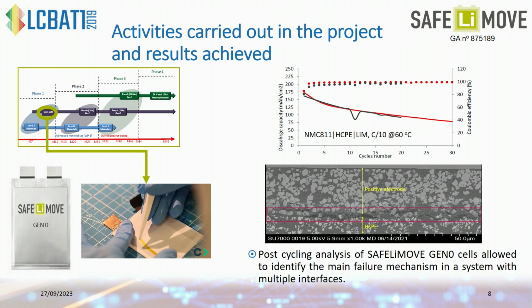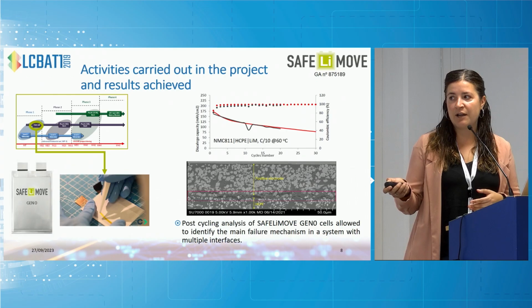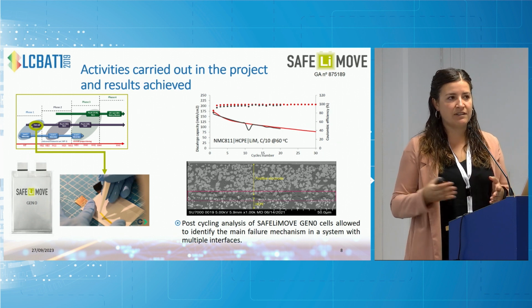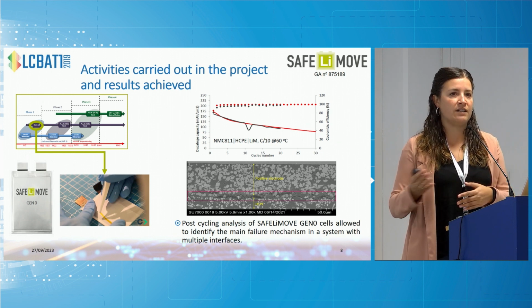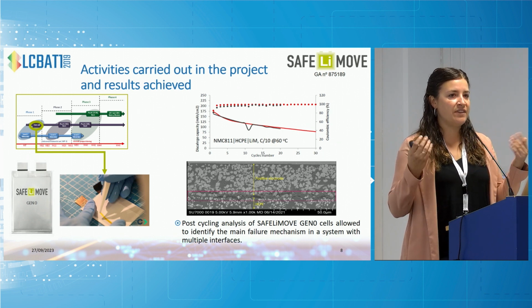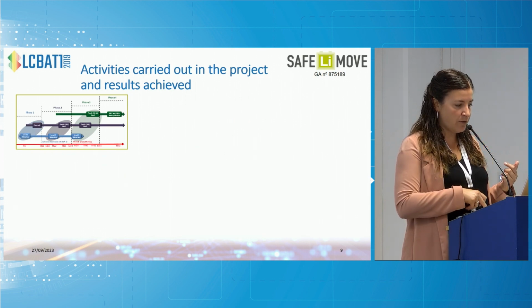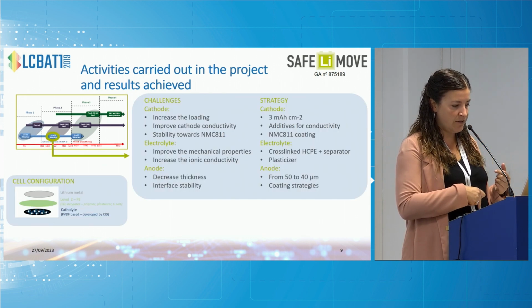And the most important part is that the cycling was used to further understand how we could progress and develop and improve the performance of the materials. So post-cycling analysis allowed us to really understand what was going on during the cycling, so we didn't have a really good interface between the electrode and the hybrid electrolyte. Also, we found some issues at the lithium metal interface. So with this guidance in mind, we worked on the development of the level 2 materials.